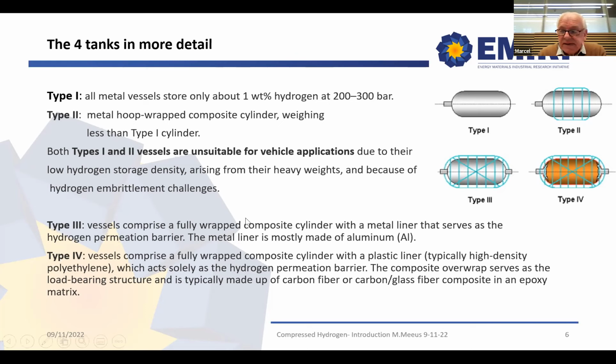Type 3 and 4 are the ones for integration in fuel cell cars. Type 3 comprises the fully wrapped composite cylinder with a metal liner, and that metal liner is mostly made of aluminum alloys. And the type 4 is the same wrapped composite cylinder, but this time with a plastic liner. And that plastic liner is typically high-density polyethylene, acting as the hydrogen permeation barrier. The composite overwrap serves as the load-bearing structure and is typically made of carbon fiber or glass fiber composite, and this in an epoxy matrix.